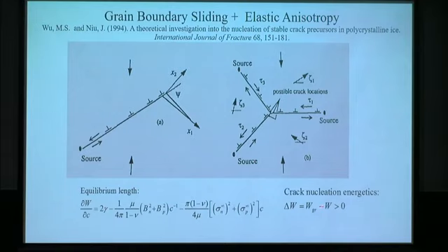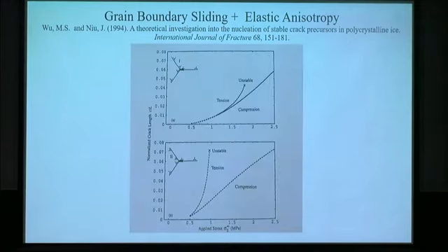Because we're going to calculate the energy difference: the energy of the pileup group, W_GR, before any crack has initiated, and W, the energy of the cracked triple junction. So we need to compare the energy before and the energy after. Of course, the scenario is more likely if the energy of the crack system is lower. With a low energy state, we can perhaps claim that the nucleation can actually happen. So that is the idea.